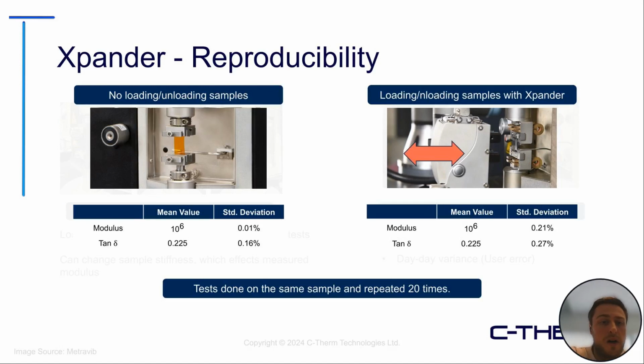So with their study, Metravib tested 20 samples. The first step was to test the same sample 20 times with no loading or unloading effects, just to see what the standard expected deviation would be. This is the same sample, not interacting with it, just running the same test 20 times. They noticed a very small standard deviation in their measured material properties, which is expected. Then they repeated this with loading and unloading the samples with the Xpander. Even though there was a larger standard deviation in the measured properties, it was still very small, less than 1% in standard deviation. I should mention too that the Xpander robot was loading and unloading the same sample every time, just to reduce the effect of inconsistencies in the material and really focus on the loading and unloading effect.